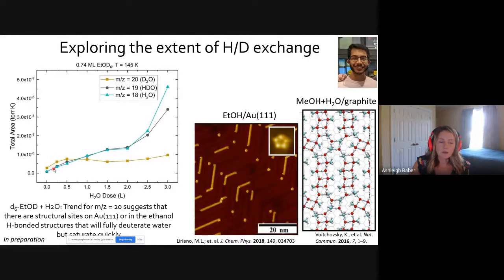And then what we see after that is as we add more water, we get more water on the surface and more water coming off of the surface. The main exchange product we see is HDO, which would be just the one exchange between hydrogen and deuterium. So again, looking at Charlie's STM images, you can start to imagine where a water molecule would need to work its way into these chains, or, because we're seeing this at such low coverages of water, is it perhaps happening within these pentamers? Is water getting within these chains?